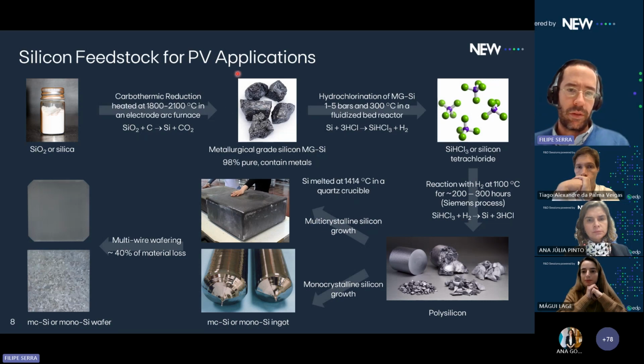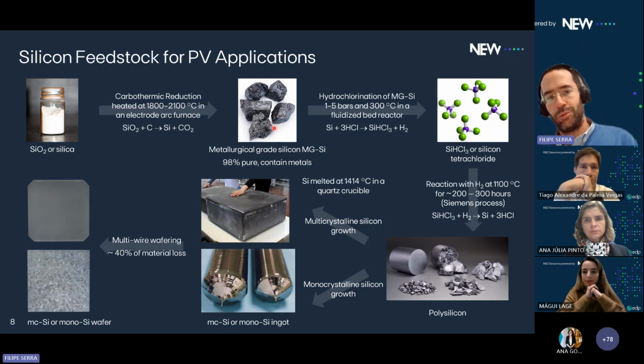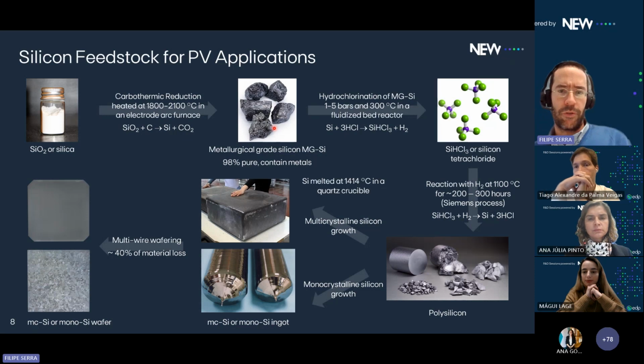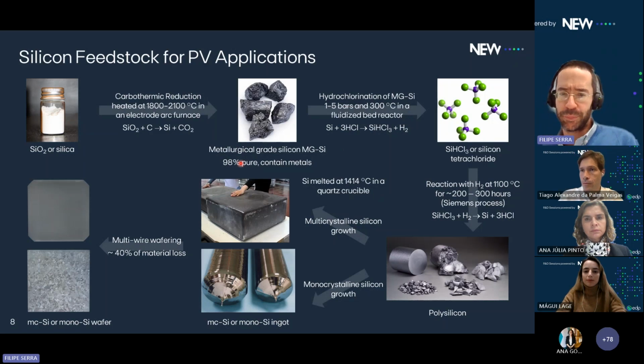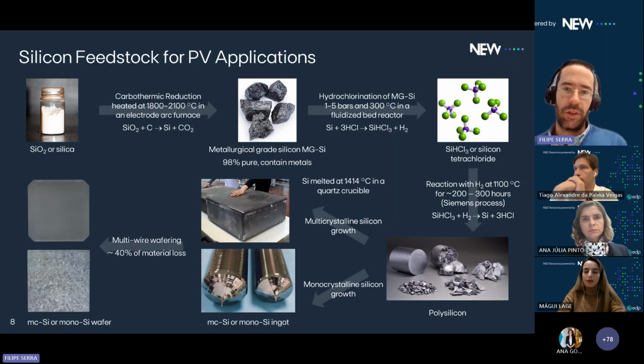After that, we obtain this type of material that we call metallurgical grade silicon, which is not ready to be used in the production of silicon wafers, because it's only 98% pure. It contains a lot of metals, alkali earth and transition metals, and also hundreds of ppm of boron, phosphorus, and other materials, so it's not possible to produce silicon wafers with that material. So in order to purify that material, we use this reaction, which is hydrochlorination of metallurgical silicon in a fluidized bed reactor.